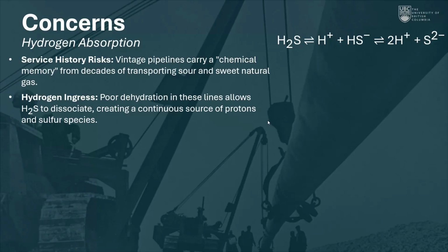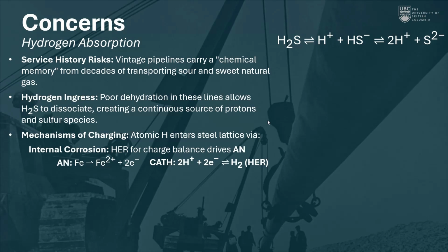And so if for whatever reason these lines had poor dehydration, we would see that hydrogen sulfide dissociates in a brine environment and forms sulfurous species as well as hydrogen protons. And so the mechanism for how hydrogen absorbs into steel occurs from two areas. One is internal corrosion. So now let's say we have an aqueous environment within our pipe. We have our anodic oxidation reaction of steel oxidation. And then to support that reaction for charge balance, we have the cathodic reaction of hydrogen evolution.